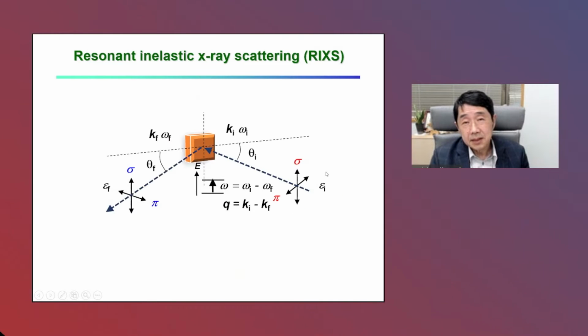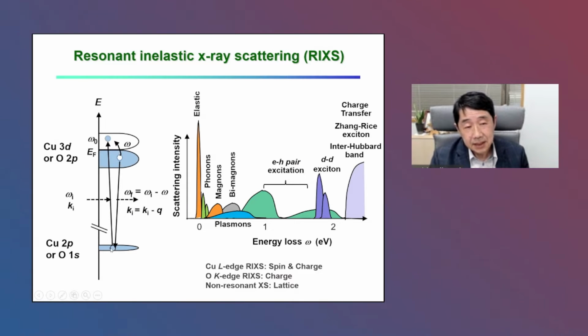And I focus on the resonant inelastic X-ray scattering. Resonant means X-ray is tuned to the core to conduction band absorption, and then this core hole is filled by an occupied electron, ending up with the electron-hole pair. In the spectra, electron-hole pair excitation is seen at high energy, like 1 to 2 eV. But the charge order can be studied by the elastic part.